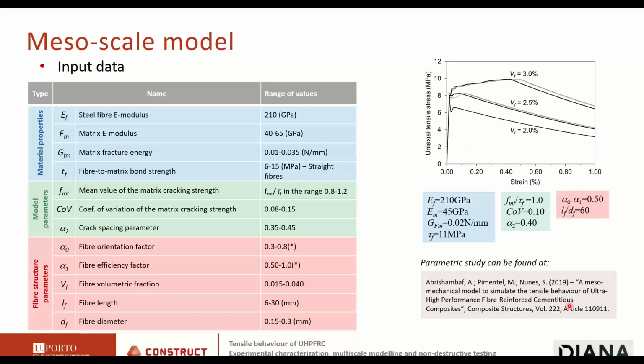Well, how does the model work? So the model requires some material properties as inputs, okay? E modulus of the fibers, E modulus of the matrix, fracture energy to get the contribution of the matrix, the fiber to matrix bond strength. Then some model parameters which are quite small. So the mean value of the matrix cracking strength. We say this is a model parameter because we introduce this as a ratio. Okay, the coefficient of variation of the matrix cracking strength and the crack spacing parameter, and then all the fiber related parameters, which are lumped in that fiber structure parameter that I just showed in the previous slide.